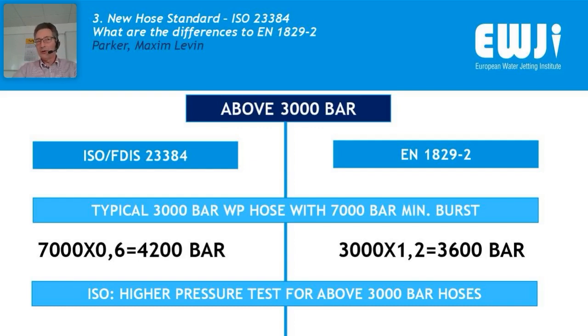And this requirement is in fact very consistent, because all the hoses with working pressures below 3000 bar are tested at 60% of burst. Very easy calculation. 2.5 to 1 design factor, so it's then 40% of burst is the working pressure. By 1.5, it's 60% of burst. And these pressure test requirements, according to ISO, is now going through all pressure classes of the hoses, which means for you as hose assembly users, on the higher pressure hoses, you will get the hoses which are tested in the same way as the lower pressure ones.